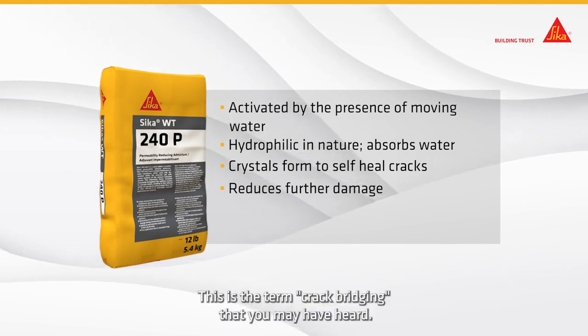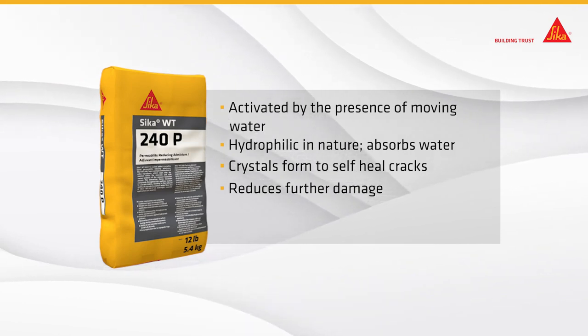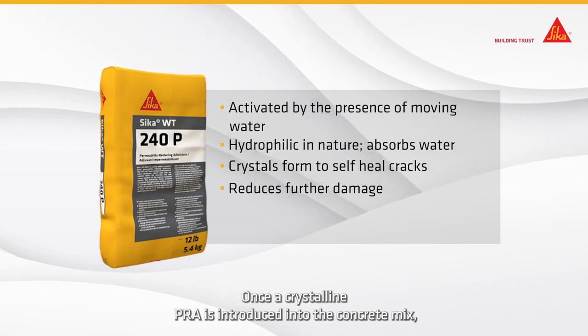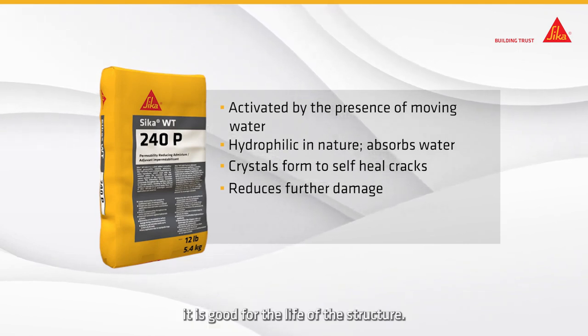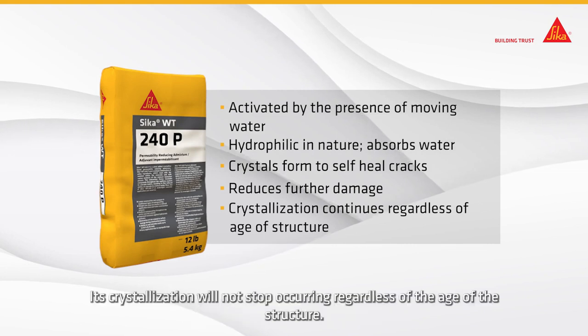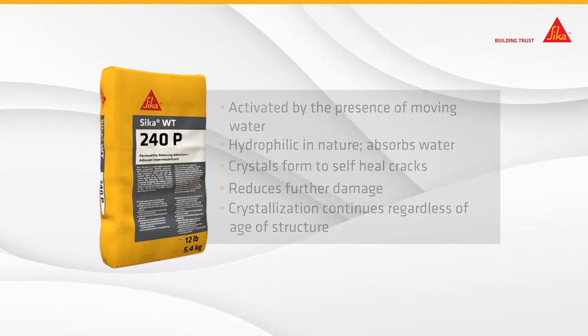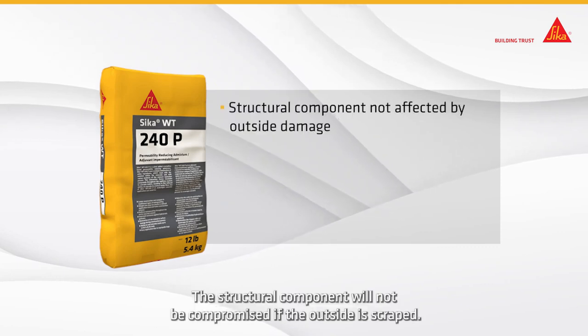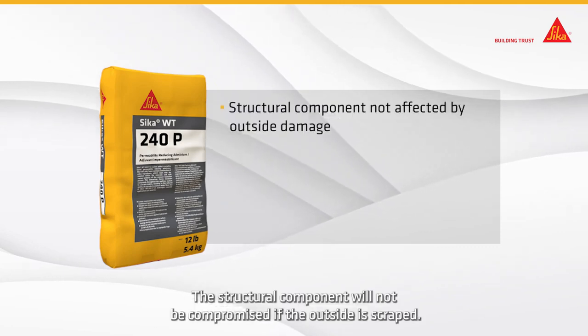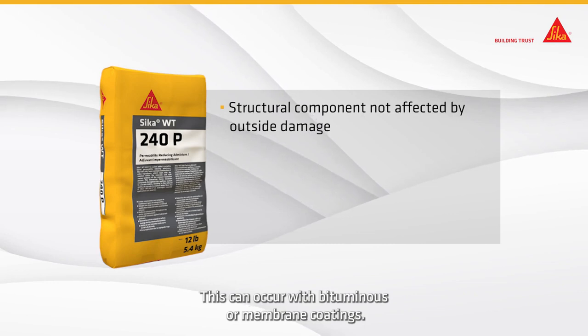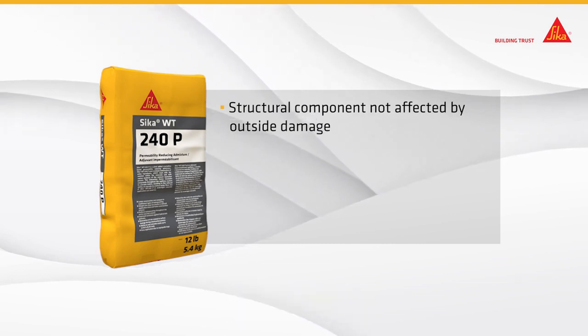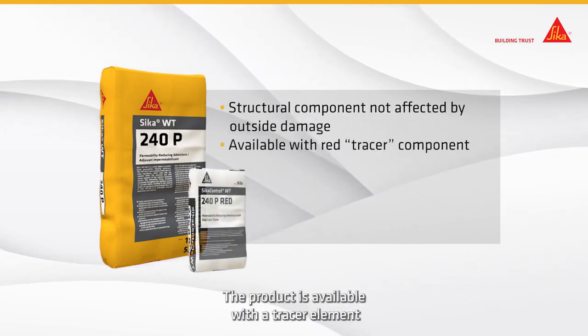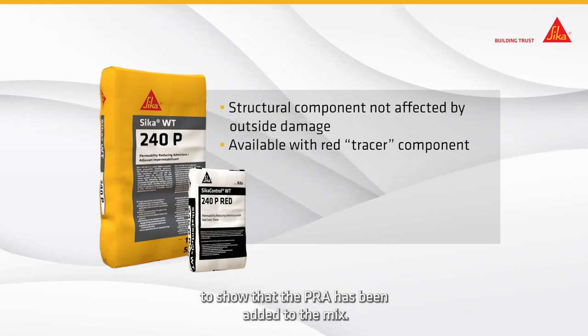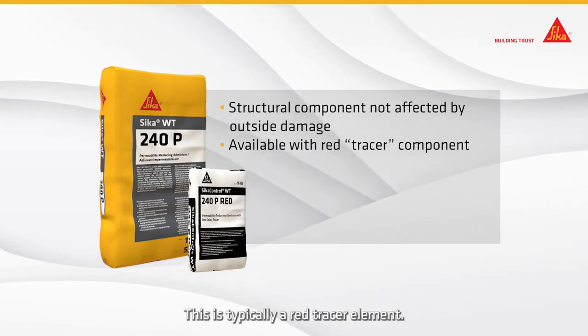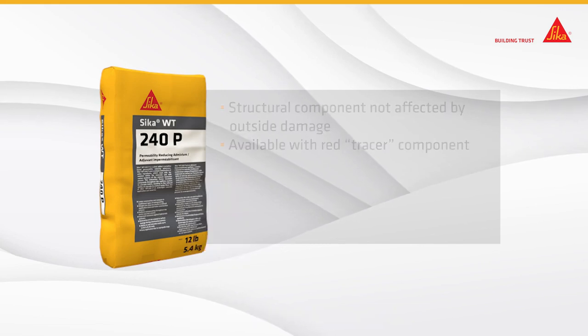This is the term crack bridging that you may have heard. Once a crystalline PRA is introduced into the concrete mix, it is good for the life of the structure. Its crystallization will not stop occurring regardless of the age of the structure. The structural component will not be compromised if the outside is scraped. This can occur with bituminous or membrane coatings. The product is available with a tracer element to show that the PRA has been added to the mix. This is typically a red tracer element.